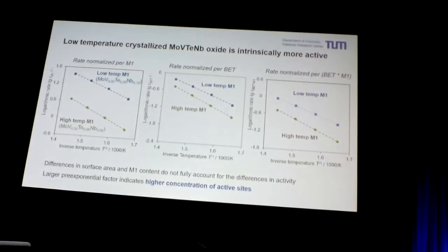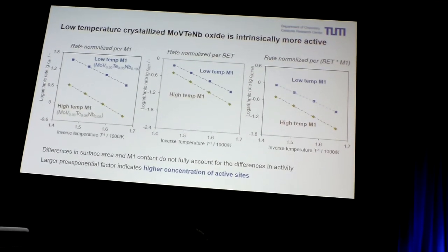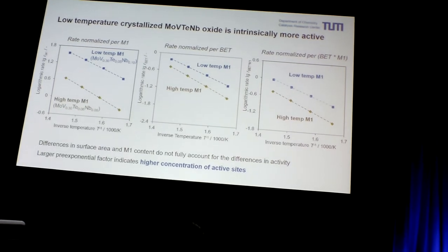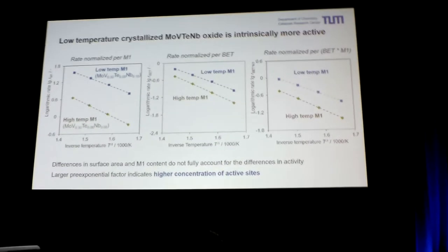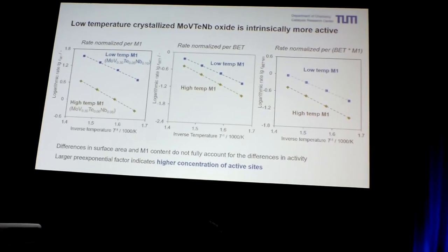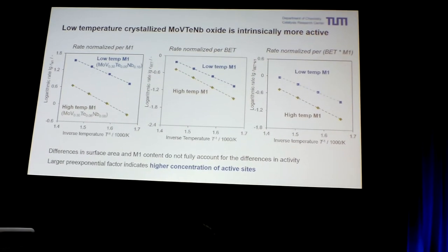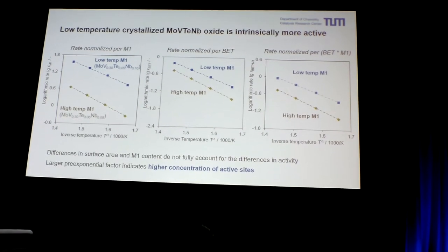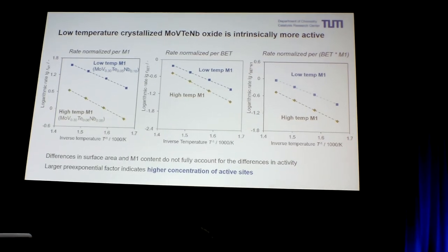In general, the Arrhenius plots are relatively parallel with similar activation energies, so we can say that our synthesis method has not changed the nature of the active site or the catalytic mechanism, but we have a higher concentration of active sites in the M1 particles.